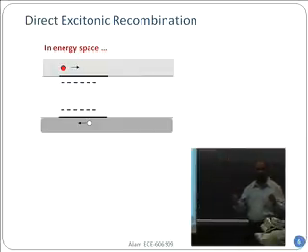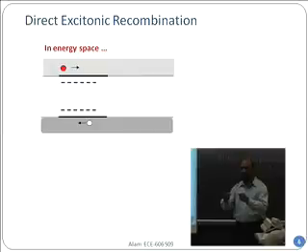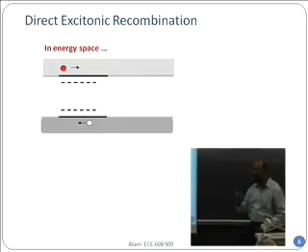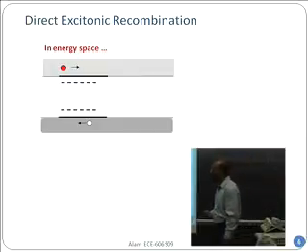So in mostly one-dimensional ones, like an organic transistor or carbon nanotube, the electrons and holes have strong Coulomb attraction. So when an electron moves around, there is a space around it in which it has this Coulomb attraction, and as soon as a hole gets into this, even though it doesn't have the same wavelength, they begin to circle each other and eventually they recombine. So this is a property of a material that has strong Coulomb interaction between the electron and hole, mostly in 1D.